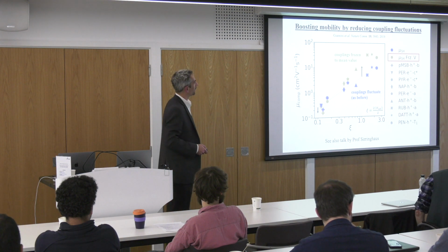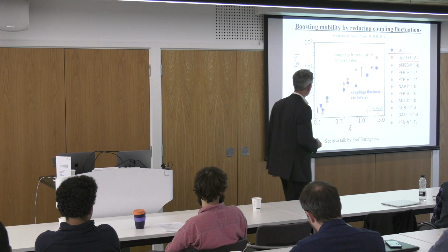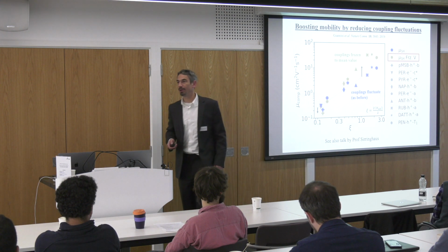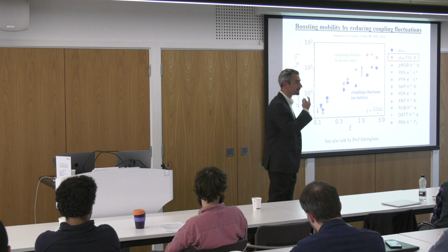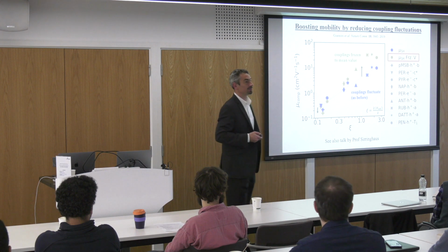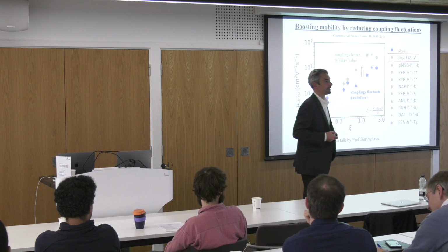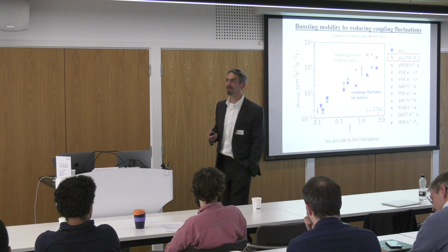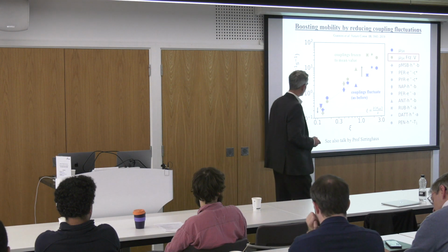Looking at these organic crystals that we have studied before, we did an in silico experiment, if you like. This is the nice thing that you can do on the computer, not so easy to do unfortunately in an experiment. We just froze all the off-diagonal electron-phonon couplings and set them to the mean value, so there is no fluctuation. And this is the result.